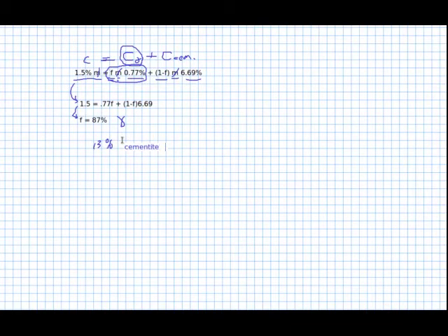And that cementite itself is 6.69% carbon, and then the remainder, which is 93.31% iron, and the gamma phase there is the austenite, and that is at this temperature for point B. Point B was picked because it's just barely above that eutectoid temperature.